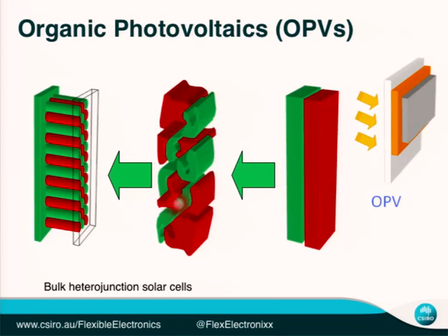But in the late 90s, a group led by Alan Heeger, who I previously mentioned as the Nobel Prize winner, discovered that you could increase the performance of these devices by making what's called a bulk heterojunction, and that's shown here. So in this device structure, you mix the two materials together, but by having a greater surface area, that creates more opportunities for charge generation. And then what you just have to do is make sure that the charges can work their way out to the electrodes. And so the final picture here is sort of the stylized image of what one day we might hope these devices look like internally, where you've got high surface area but continuous pathways for the charges to the electrodes.